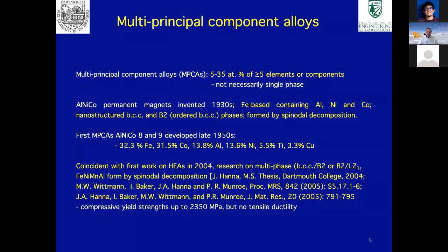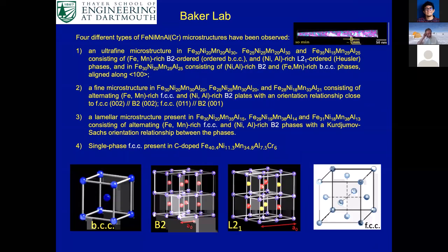We started work on structural materials in around 2004, when we produced some spinodal alloys with a really fine microstructure, very strong, up to 2300 MPa, very little ductility. So just a brief overview of what we've done in my lab. We've really looked at 4 types of microstructures. So we've looked at these ultrafine microstructures, which are formed by spinodal decomposition. Here's an image of one here.